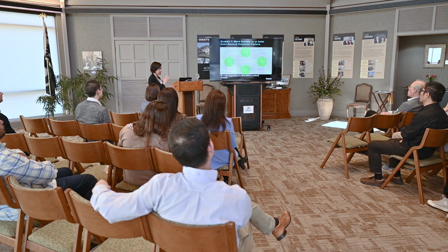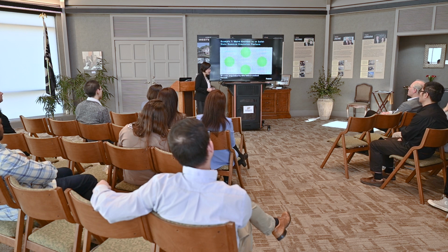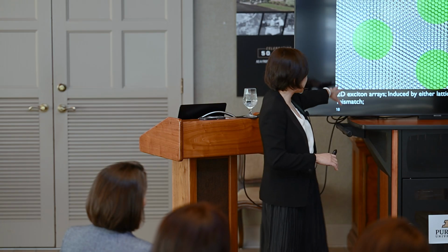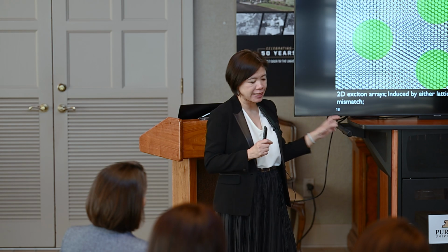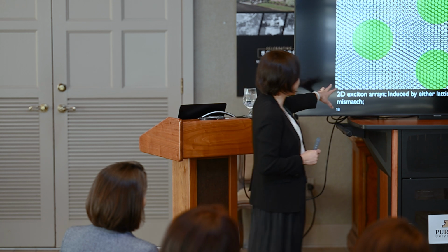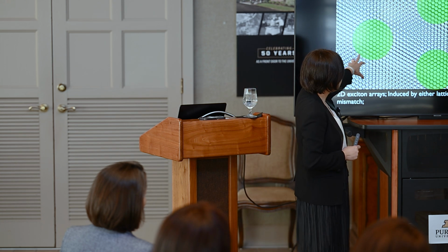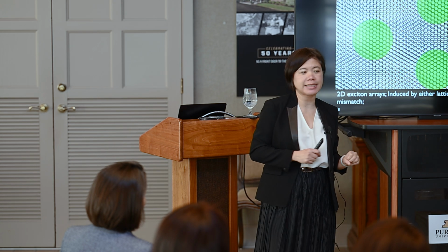Okay, so the first model system that I'm gonna share is excitons in these 2D sheets that I discussed. These are two-dimensional single-layer semiconductors, and in particular in this case a layer of tungsten disulfide and tungsten diselenide. If you layer two different materials on top of each other, in this case two lattices with slightly different lattice constants, you generate a new superlattice. The green dots are where these new superlattices are.